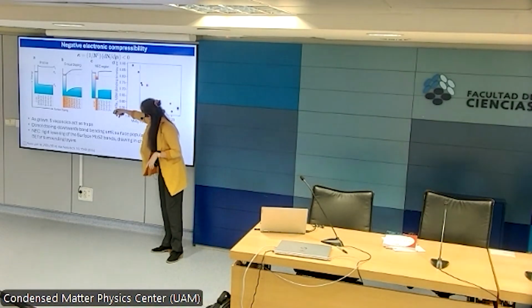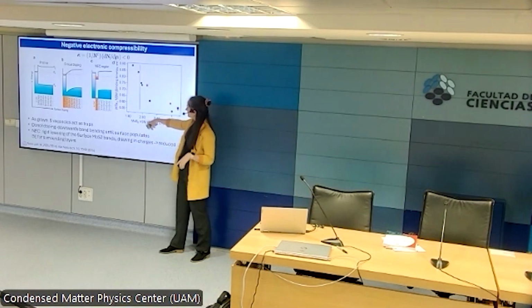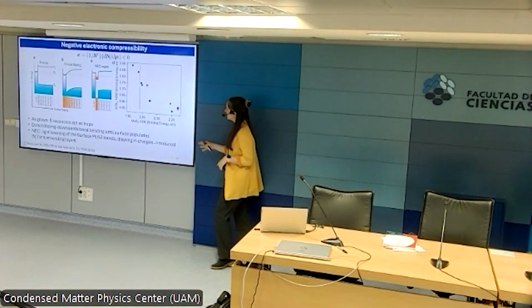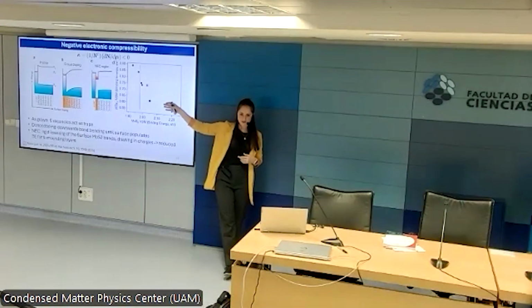And this is to tell you, basically, this is the position of the topmost valence band of tungsten ditelluride and the topmost valence band of molybdenum disulfide. You can see that they have an inverse correlation, so this trend of the bands getting closer or further away according to the doping is confirmed. Different symbols are different samples grown in different years on different beam times, so this is definitely true.